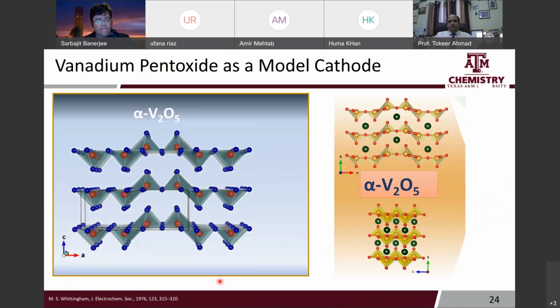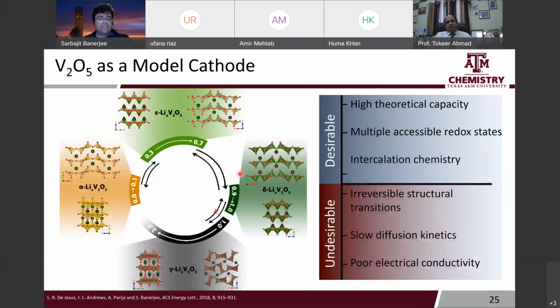So I'm going to start with one cathode we particularly like, which is alpha V2O5. So Stan Whittingham, in some very seminal work back in the 70s, proposed using this as a cathode for lithium-ion batteries. Why? Because it makes all sorts of sense. You've got lots of open sites here. You've got vanadium here, which you can reduce from vanadium 5+ to 4+ to 3+, and even lower if need be. And so this seems to make a lot of sense. But then it turned out not to be so great. Why is it not so great?